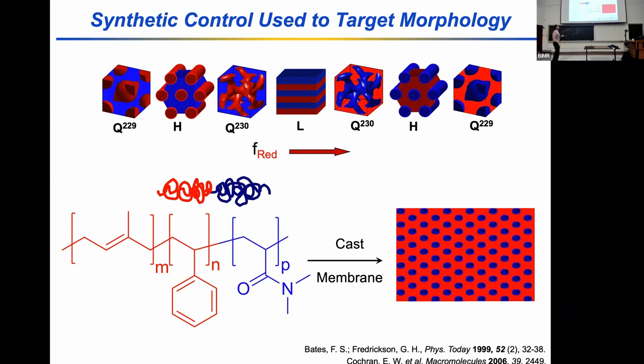And that conformational entropy means that they can't phase separate across large length scales, and instead they microphase separate to form a variety of nanostructures like those you see along the top of this slide. Primarily, the thing that determines what nanostructure you'll form is the relative amount of red block to the relative amount of blue block. We're going to be working with about 75% red block and 25% blue block, which forms these hexagonally packed cylindrical microdomains, where the cylinders will be what become our polymer membrane.